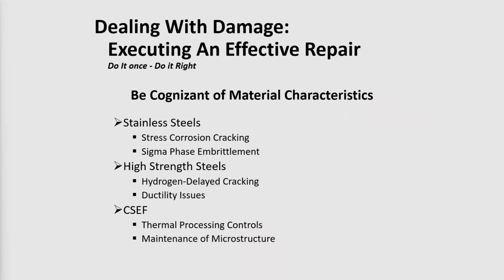And then finally, be cognizant of material characteristics, depending upon what type of material you're dealing with. There are a few austenitic stainless steel systems out there, so things like stress corrosion cracking or sigma phase embrittlement could be considerations that would be taken account of in any kind of repair, because failure to do that would result in a failed repair. High strength steels, things like hydrogen delayed cracking, or the enhanced susceptibility to hydrogen delayed cracking should be taken into account. There may be ductility issues that need to be accounted for.